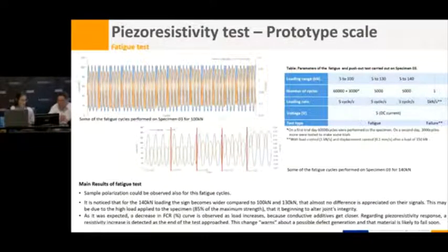This is the fatigue test. When designing this kind of joint, designers or engineers take into account more or less 60% or 70% of the failure load. So in the first tests, these 100 kilonewtons and 130 kilonewtons correspond to 60% and 70% of the failure load. But after more than 60,000 cycles, we didn't see any change, any failure in the joints. So we tried once again to go a little bit further, to a maximum of 85% of the failure load, to create a very aggressive environment.